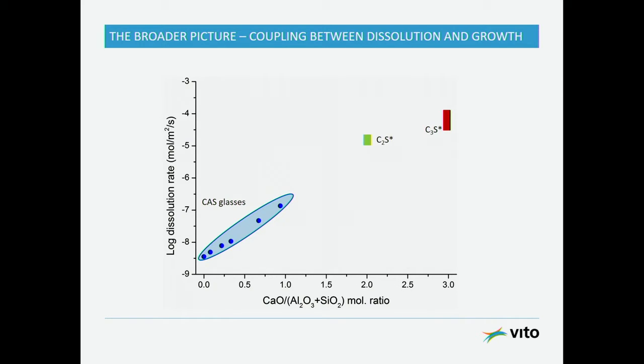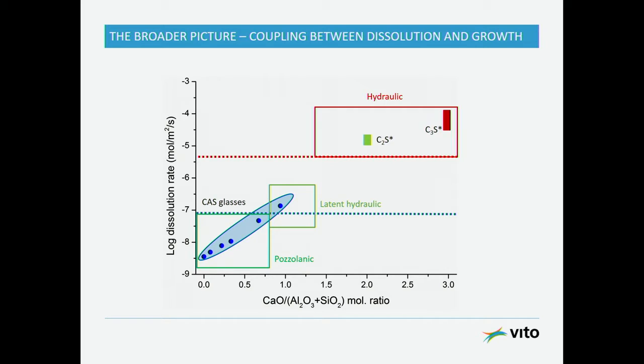One can actually also look at, okay, what if we put it in a broader picture, like what are the dissolution rates here, and what is then here the calcium to aluminum plus silicon molar ratio. And then these data here above are from Nicoleau, for instance, from dissolution experiments, and here these are the data I showed you before. And one can actually distinguish 3 different regimes as well.